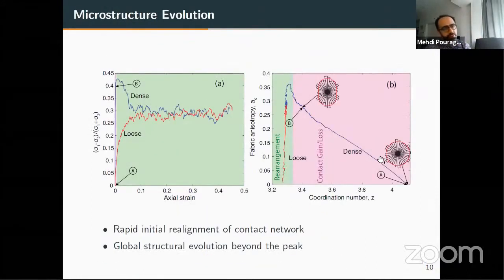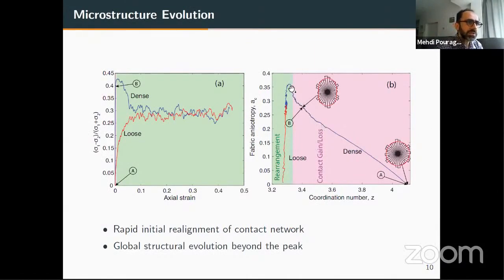One thing which was interesting to me, and it was the start of this sort of reasoning, was that we can see that the structure starts to evolve when the state of material in the micromechanical space is aligned with the loose sample. You see, for the loose sample, the coordination number is increasing a little bit from this point to that point, and this is the critical state. This is a steady state at the end. It's called critical state in soil mechanics. So we see that the large deformation starts to take place when the state is more or less aligned with this line. So there seems to be something meaningful associated with that line.